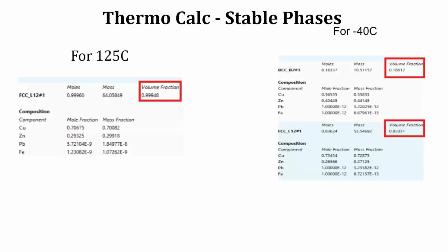So, looking at the ThermoCalc data, for the 125 degrees Celsius from the thermal cycling Lear provided us, we have 99.94% of the brass in the FCC phase. And then once you get to -40, you see a phase change to where most of it is still FCC, but then some is a BCC atomic structure.